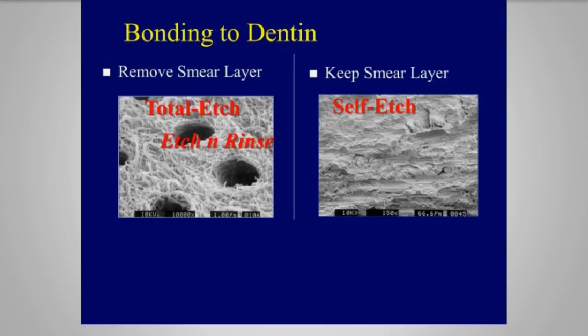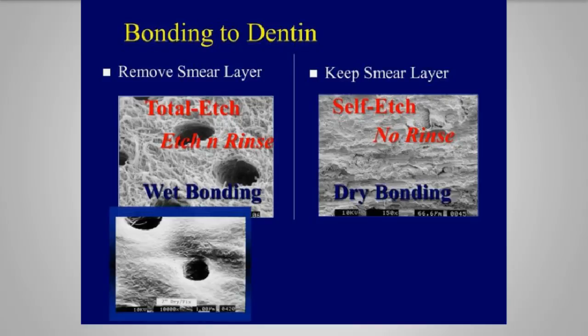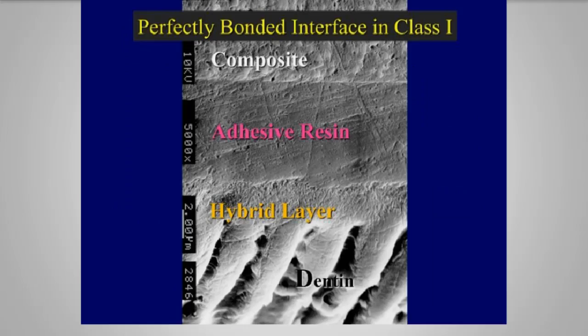Etch and rinse, wet bonding. The other one is no rinse. I am a subscriber to selective etch, rotary abrasion of virgin enamel, and using 7th and/or 6th generation adhesion. So one way we can over-dry the dentin, collapse the collagen fibers, and then your bond strengths are very marginal and inadequate at best. Collapse collagen.